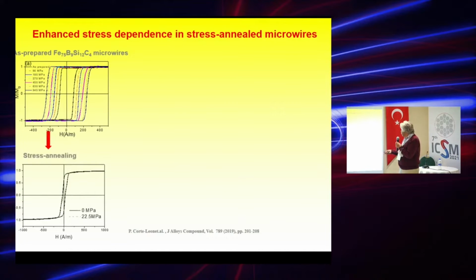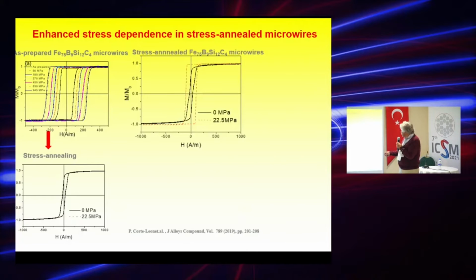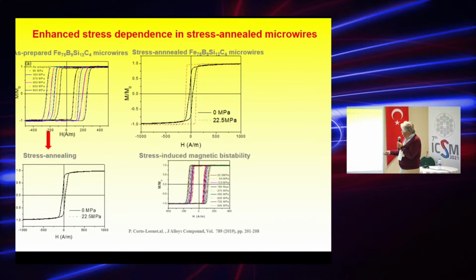What happens now if we apply stress to stress-annealed samples? So after stress annealing, our samples are no longer magnetically bistable, as shown in these pictures. It's close to bistable, but not bistable. And now, if you apply stress, the hysteresis loop becomes bistable again, even at small applied stresses. So this is with the lowest value, and then for increased stresses, it behaves similarly to the as-prepared sample. So in this case, applied stress is quite relevant because it allows us to improve the stress sensitivity of that material.